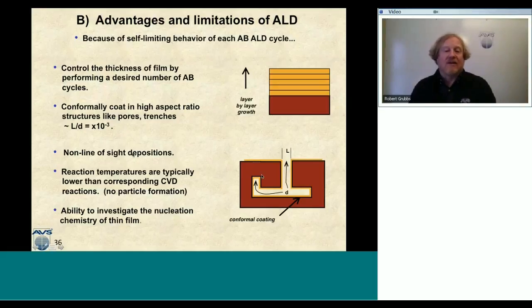on the surface. Now, mind you, that when we're coating high aspect ratios, the amount of flux, the amount of exposure on the surface is going to be higher than it is down in one of these trenches. So you might see a little thicker film growth on your surface than you would down in this trench, just because of the sheer amount of chemical exposure and the soft saturation of the chemistry.